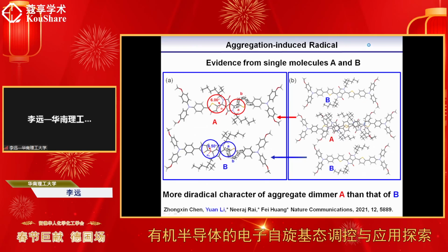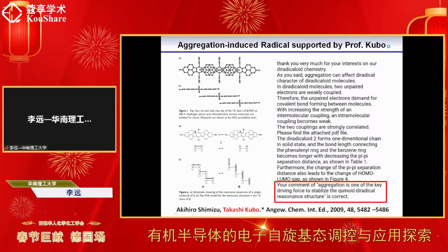And Professor Kubo is a very famous researcher in the field of polyaromatic hydrocarbons, and we can see his comment: aggregation is one of the key driving forces to stabilize the quinoid radical resonance structure. This is correct. For his very old system, as we know, he published many papers on this kind of radicals about 15 to 20 years ago, for polyaromatic hydrocarbon radicals. And in their system, aggregation is also a very key factor to stabilize the quinoid radical.